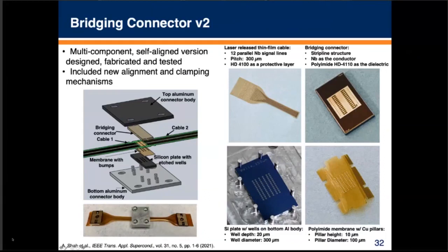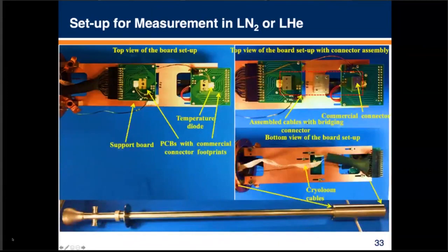You can see the traces here in the top ground. There's a bottom ground there as well that you don't see. This piece has some small little wells in it, and then there's a piece of polyimide that has copper pillars on it. Those reside over the top of these wells, and the tapes sit on top of that, and those little copper pillars then push the tape up against the location that it needed to connect on the connector. That was the approach for our second connector structure. You can see it here. Here's our measurement setup in these boards, where we have these two commercially available connectors that everything is attached to and mounted in this immersion probe as well.